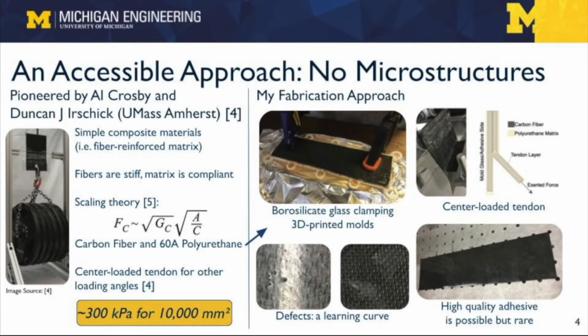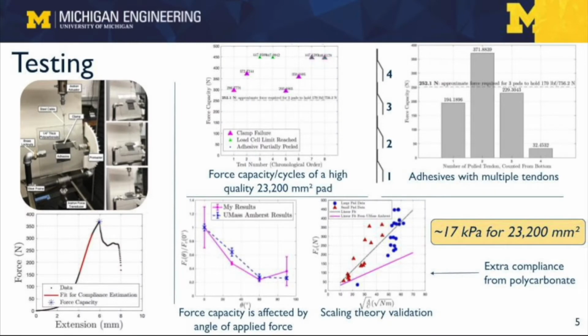But my approach was not perfect by a long shot. My fabrication method produced a lot of defects on the adhesive surface, and I was only able to get one high-quality adhesive about one time in 20 tries. But once I had this high quality adhesive, I was able to perform testing on its ability.